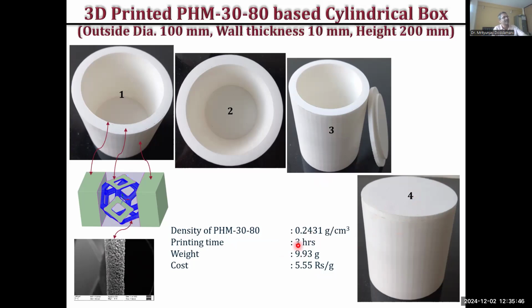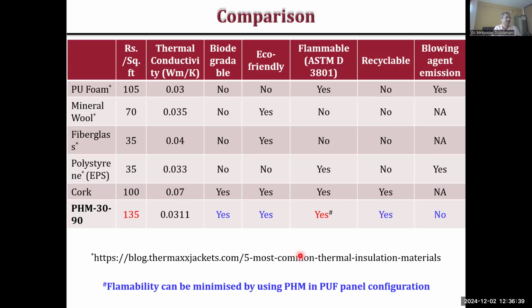The reason being the maximum printing speed was around 20 millimeters per second. Nowadays, it has increased substantially because this was the printer which I procured in 2016. So nowadays, printers have higher printing speeds. I have just shown a simple vessel here. You can have any complex intricate shapes produced because we need to just feed a CAD drawing to a printer. But if I want to go for injection molding, based on a small change, we need to produce an entirely new mold cavity. So that doesn't come into the picture. Tooling cost is 0 in 3D printing. And this is the structure available inside with the foamed parameter, and that's how it gives us 0.0311.